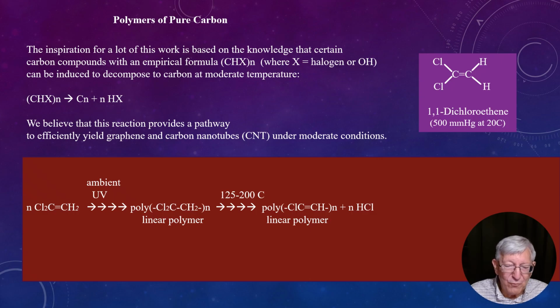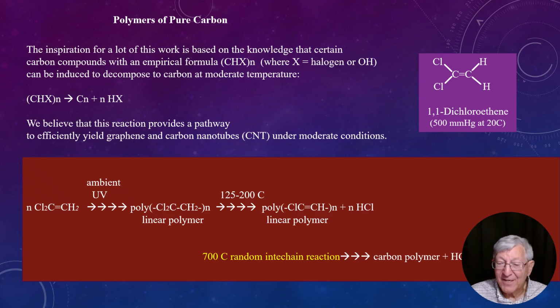And the real problem here is that this temperature range you could reach with a microwave or with an oven, and so your typical housewife was likely going to cause problems with this. And so the product was dropped, not pursued, because of the problems with its instability. Now, it turns out if you continue heating this, you can drive all the HCl out. Unfortunately, I am in the middle of this and you can't see the end of that.